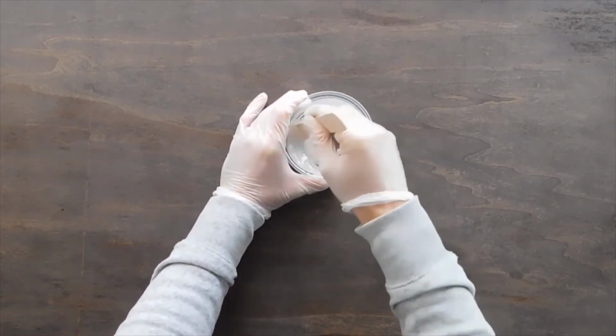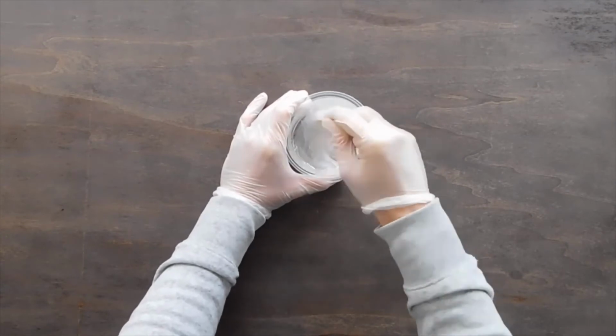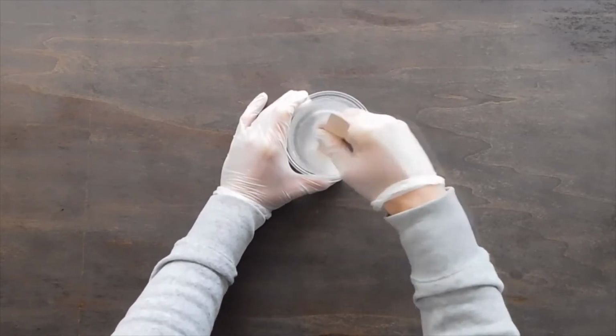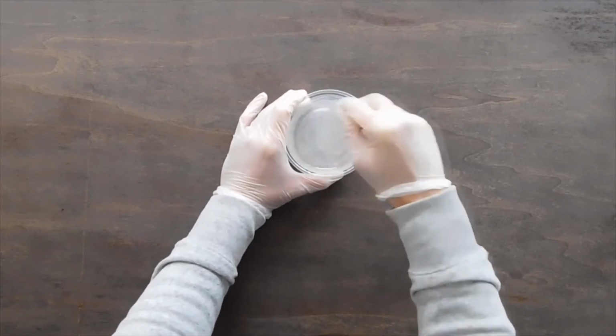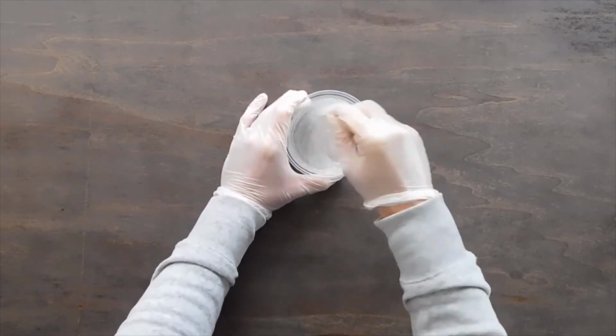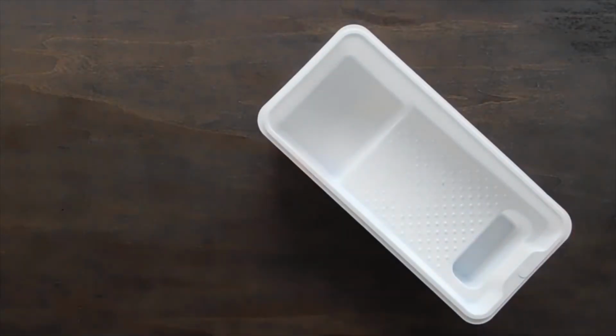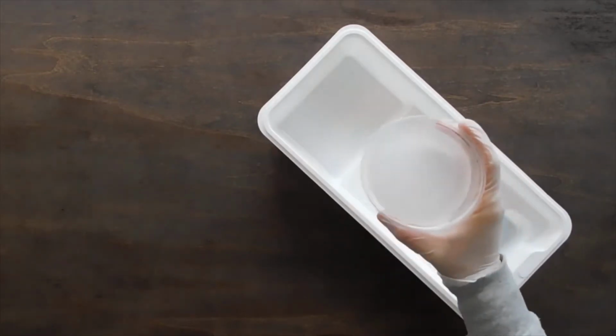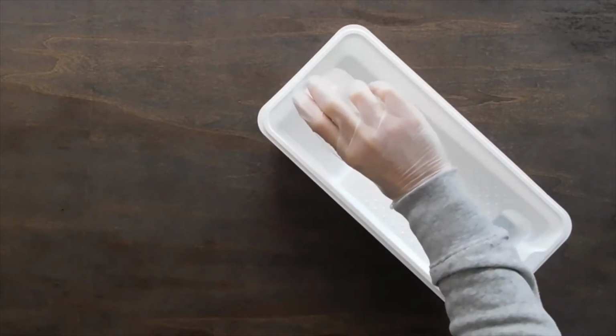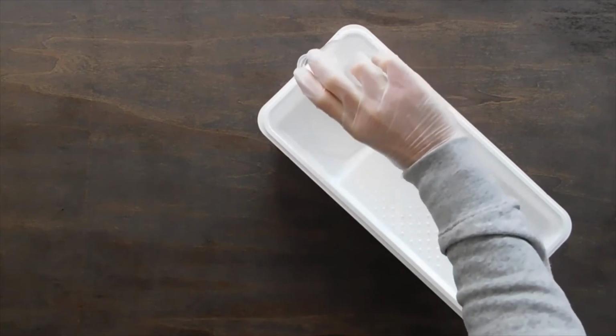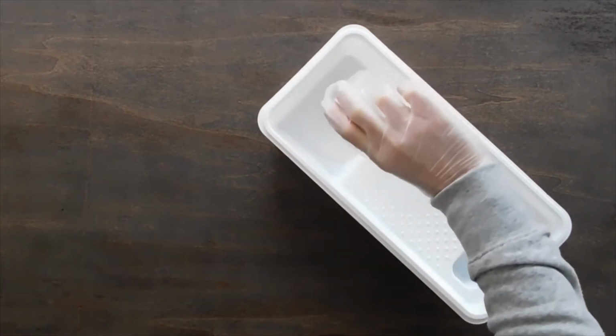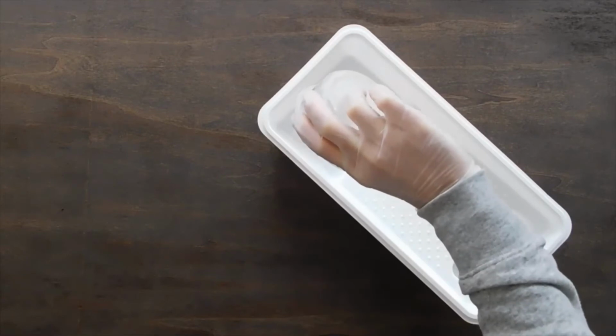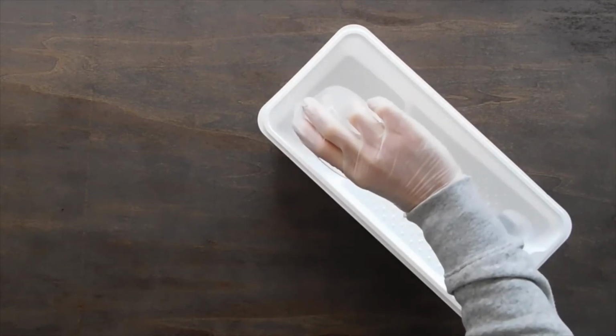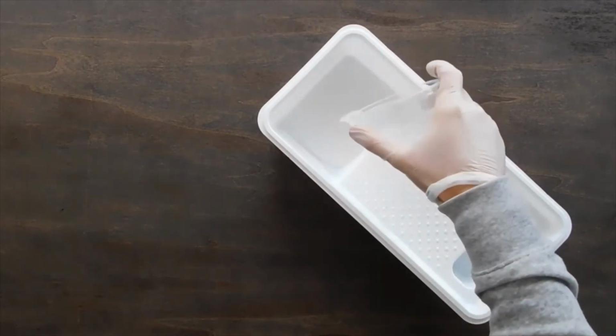It is typically recommended to add an amount of SRC18 catalyst that will eventually cause complete cure of the adhesive. 2 parts per 100 is a good starting point. Adhesive completely cured with SRC18 catalyst will be tack-free, and as such will not bear the properties typically required for making tapes or transfer films, but should meet the requirements of contact adhesive applications. However, generally speaking, the less catalyst used, the better the damping properties. If your application allows, you may want to experiment with various catalyst loadings when trialing your optimal formula.